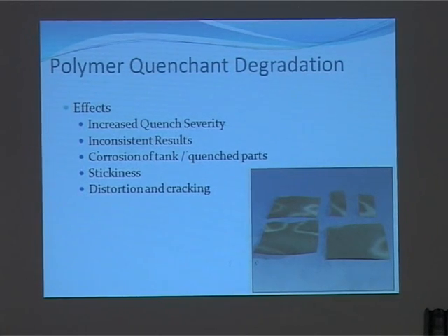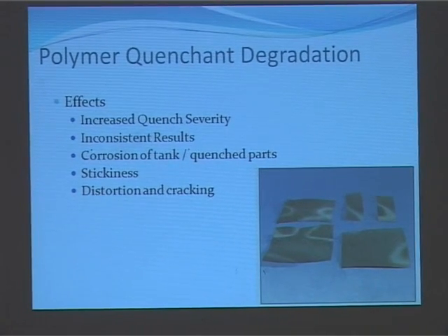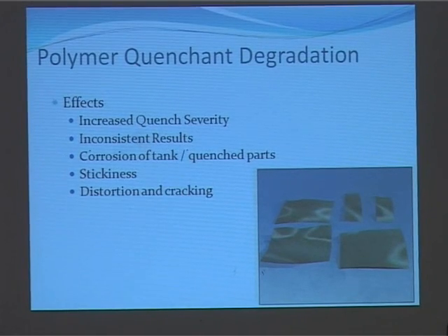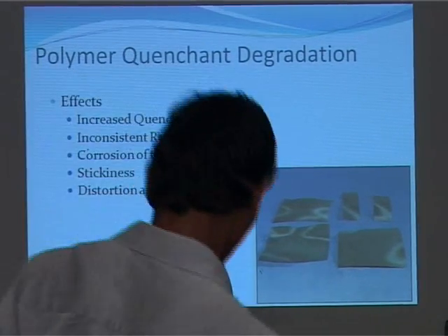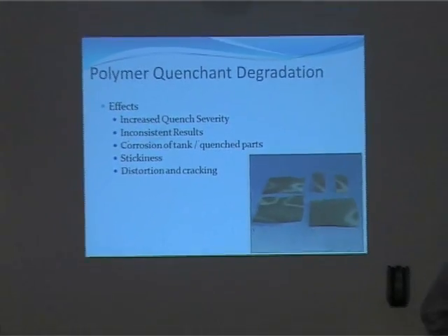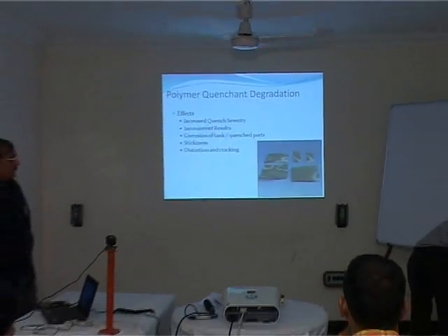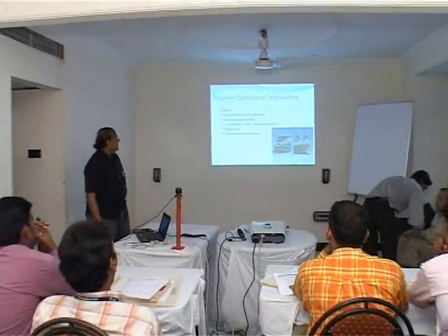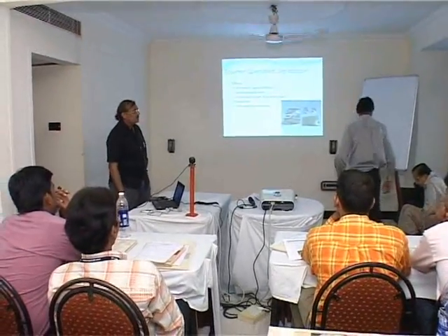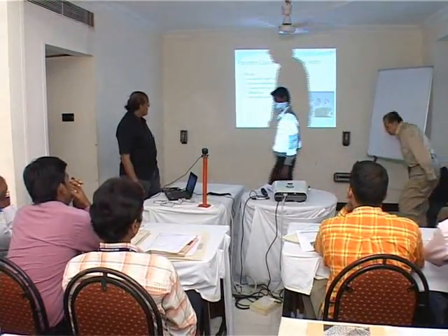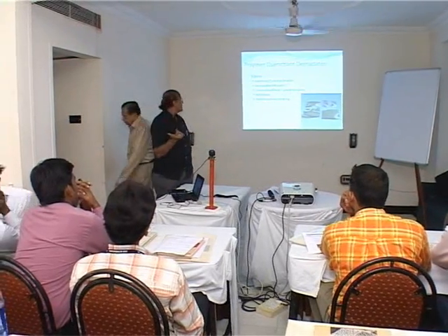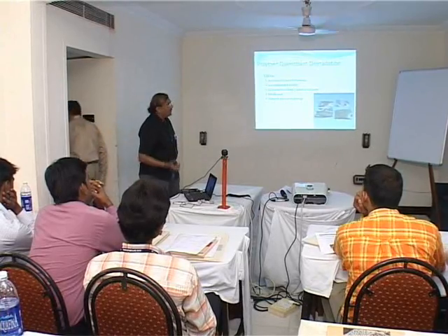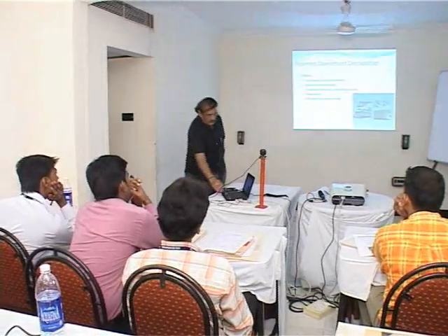If your polymer quenchant has degraded, these are the effects you will find. The quench severity will increase. You will not get consistent results. Corrosion of the tank will start, and the quenched parts may start getting corroded. The polymer gets stuck on the surface, and distortion and cracking start on the surface.